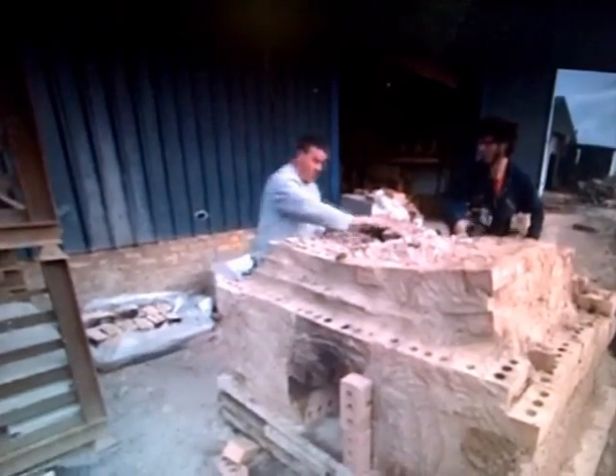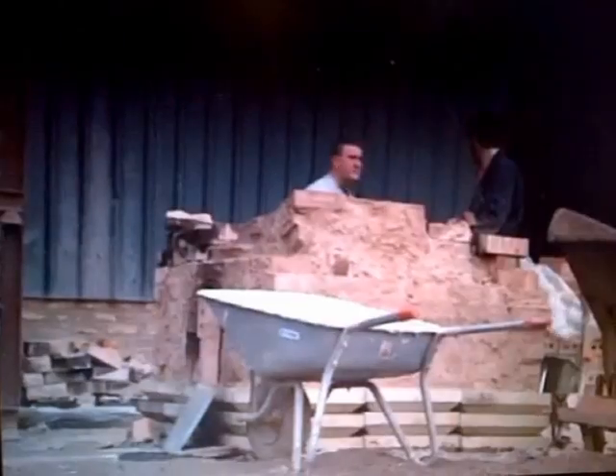It reached temperature the previous night, so hopefully there'll be a good firing. The bricks are looking a bit soft. They use a test of tapping two bricks together — if you get a ringing noise, they're all right. One comes up unfired, but overall about 80% of the bricks could be used. That's just as good as modern-fired bricks. The biggest risk with under-fired bricks is frost attack, but as these are going inside a boiler there'll be no frost to worry about.